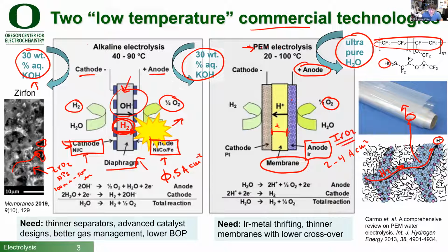And even iridium oxide slowly dissolves and is one of the factors that limits the lifetime of proton exchange membrane electrolyzers. And iridium oxide, we only mine about 7 tons per year. And it's very expensive, about $5,000 per ounce. And an ounce is about 30 grams or so. So it's very, very expensive material.